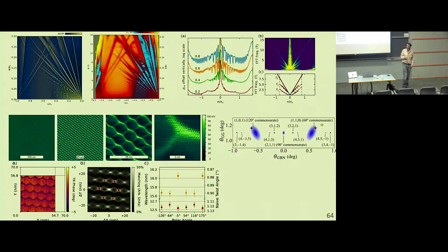Yeah. So is it in contact? It is in contact. So we are feeding back, we're pressing in with a force, and it turns out that what's important is the pressure that we're pushing with. Depending on how sharp the tip is, if it's a sharper tip, we don't need as much force. So we're pushing and feeding back on that force, and then we're oscillating in this direction and tracking the corresponding motion.